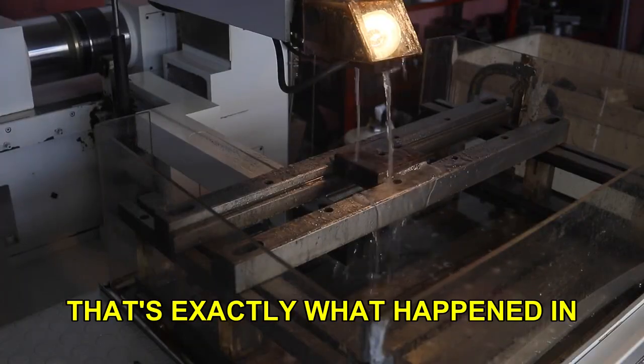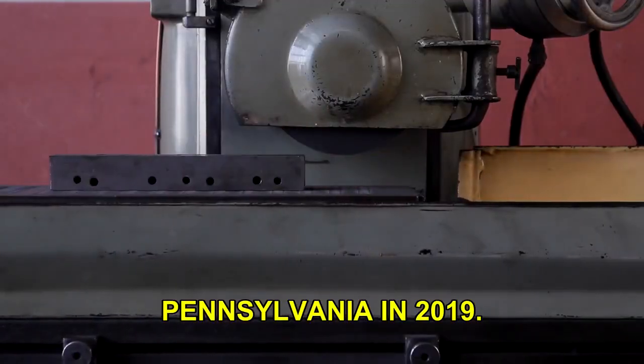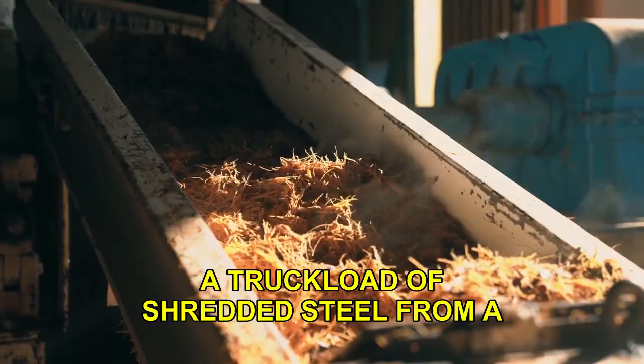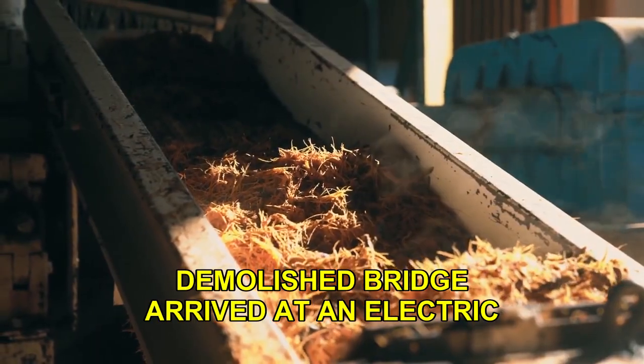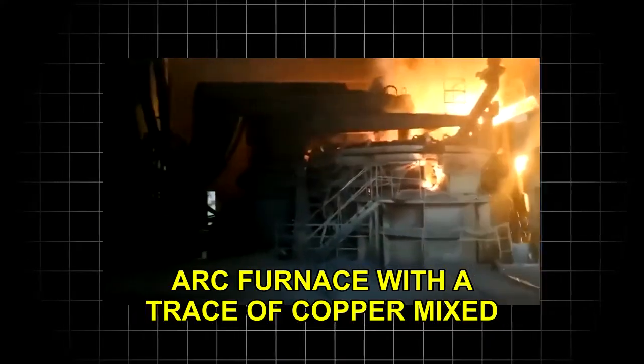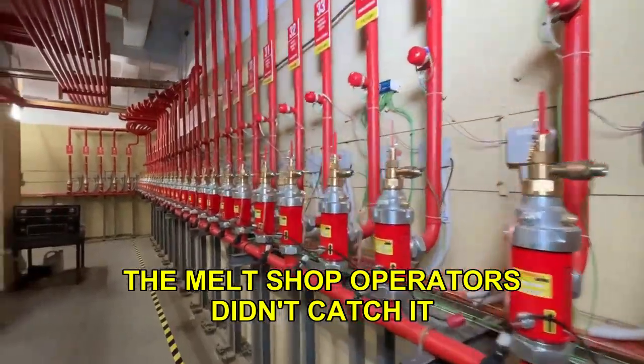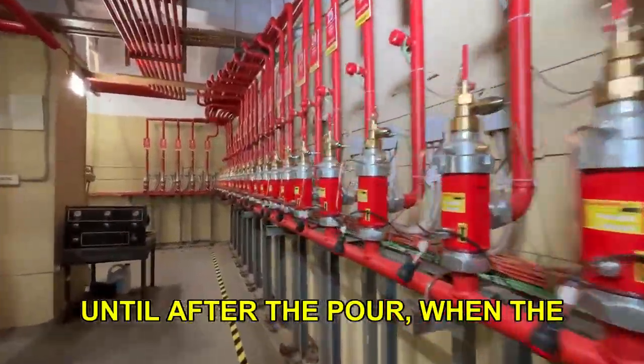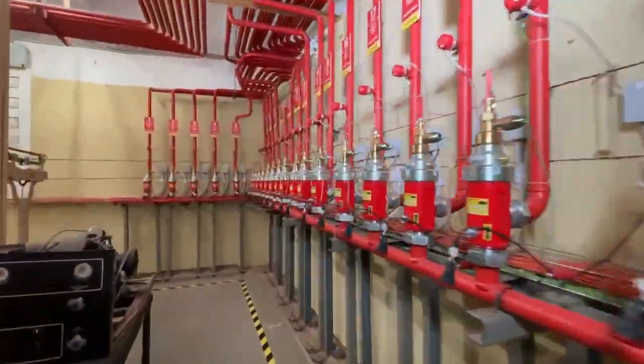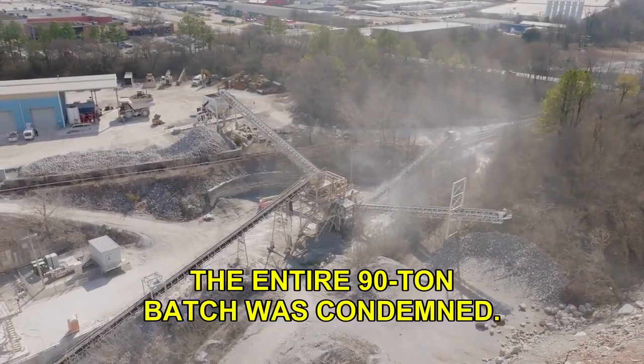That's exactly what happened in Pennsylvania in 2019. A truckload of shredded steel from a demolished bridge arrived at an electric arc furnace with a trace of copper mixed in, just 0.3%. The melt shop operators didn't catch it until after the pour, when the spectrometer screamed a red alert. The entire 90-ton batch was condemned.